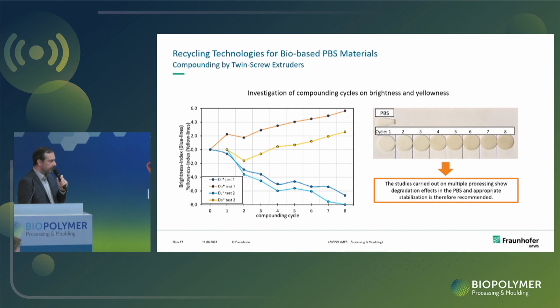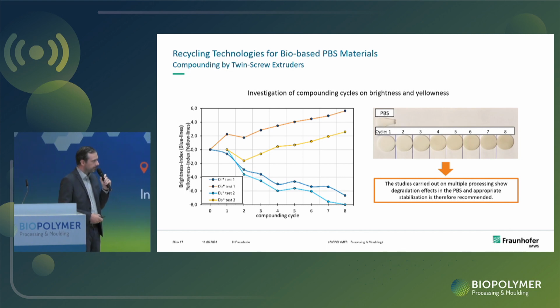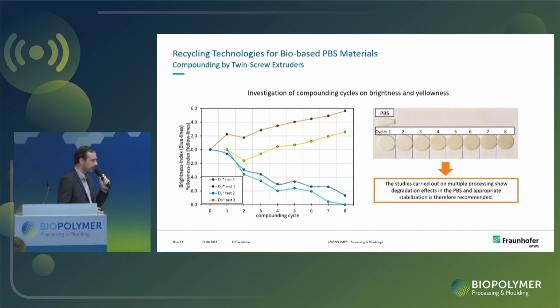Good. Also a very important question is the appearance of the material, so the coloring and so on. Here you can see that with increasing compounding cycles, there is a change in the brightness and in the yellowness. The brightness is the blue lines, meaning with the ongoing compounding cycles, the brightness goes down, so the material appears darker, and the yellowness goes up, so it gets darker and more yellow. You can see this on the right side in the pictures. And we learned today in another lecture that there are modifiers and additives which should be used to modify the material and keep this problem under control.